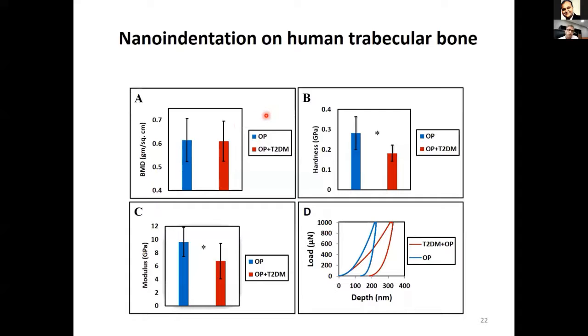It means we need something else, and this is what the surgeons and clinicians were talking about, that there is something else, because they find that the bone is not so deteriorated, but DEXA is not able to tell us. So we have done this indentation and found out the hardness. You can see that osteoporosis has, but if osteoporosis plus type 2 diabetes, which generally happens because osteoporosis is related to age, and type 2 diabetes also most of the time happens at an older age. So if we have both these cases, then the hardness gets reduced significantly, as well as the modulus, which is not conveyed by the DEXA.